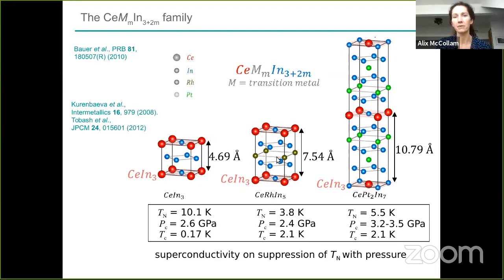The 115 materials are the next member of this family, with a layer in between. This is tetragonal, and this is extended tetragonal. It's body-centered tetragonal, but it's a more two-dimensional version of the 115 members of the family. So cerium platinum-2 indium-7 is the material that I'm going to talk about. And all of these materials become superconducting when you suppress with pressure.